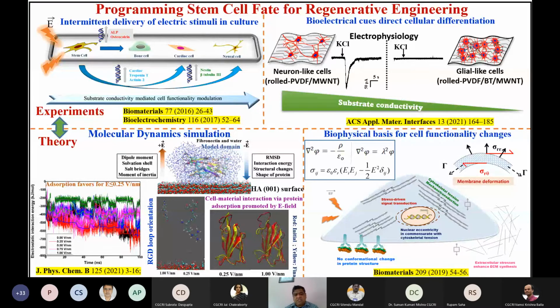Now, the question remains: when you give this electric field, what would happen to the proteins adsorbed on the biomaterial substrate, and does the protein get denatured? To address this, we have done a molecular dynamics simulation study in collaboration with Prabal Maiti's group at the Physics Department, IISc, and we have calculated the electrostatic interaction energy. Molecular dynamics simulation studies are typically restricted up to 100 nanoseconds; for longer time periods, they need really extensive computational power. So in this particular MD domain, we have also found the RGD loop orientation and how it changes with changing electric field strength.